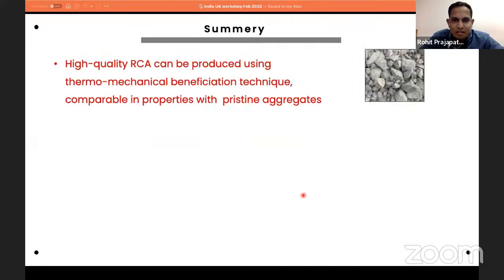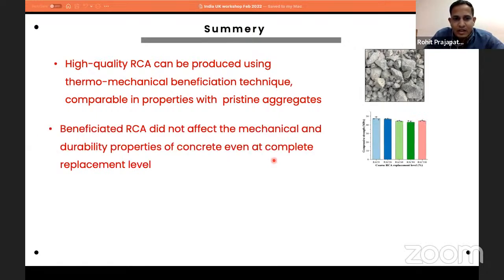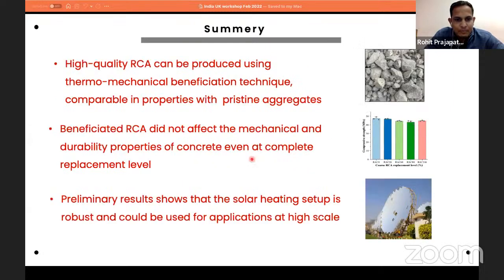So to summarize the results, high quality RCA can be produced using this thermomechanical beneficiation technique, and the properties could have comparable performance as the pristine aggregates. And the beneficiated RCA did not affect the mechanical property, and more importantly, the durability. It was found similar even at 100% or complete replacement. And the preliminary results show that for the solar heating setup, all the trials were robust, and there is a possibility that it could be used in applications at high scale.